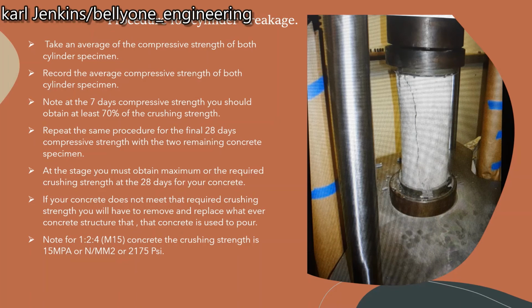In the event that you're not getting close to 70%, it does not mean that your concrete specimen has failed. You must wait until you do the 28 days compressive strength to know if the concrete specimen has failed or the concrete is too weak for your structure. So you're going to repeat the procedure for the 28 days compressive strength with the two remaining concrete specimens. At this stage, you must obtain the maximum or required crushing strength at 28 days for your concrete. At 28 days, that is the final setting time for your concrete specimen. And when you break your concrete cylinder specimen for that 28 days, you must get the required concrete strength. If your concrete does not meet that required crushing strength, you will have to remove and replace whatever concrete structure that concrete was used to pour.